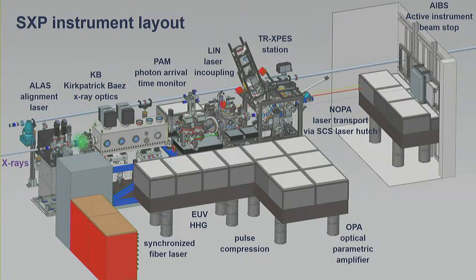We have a focusing for X-rays, a KB system in this case. We have a pulse arrival monitor to measure the relative arrival time between the optical laser and the FEL. We have a laser coupling system to couple the optical laser into the system, and here we have the experimental station that is equipped with a momentum microscope in the vertical configuration.